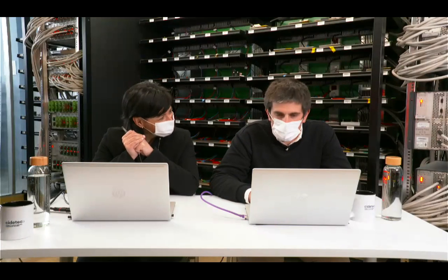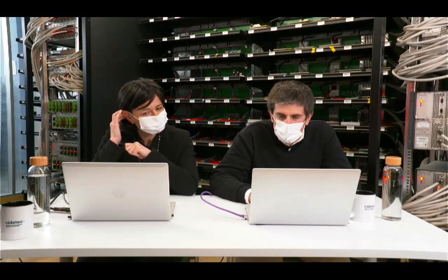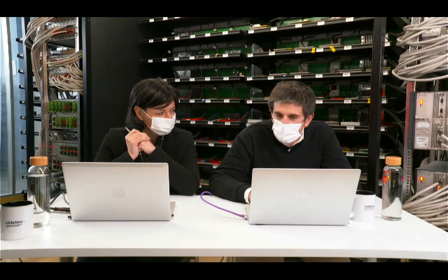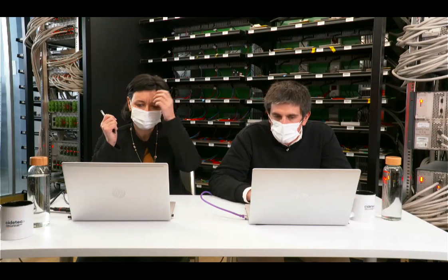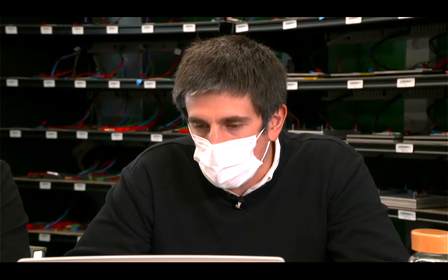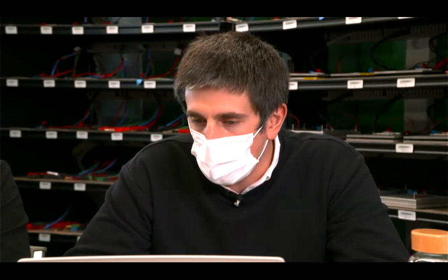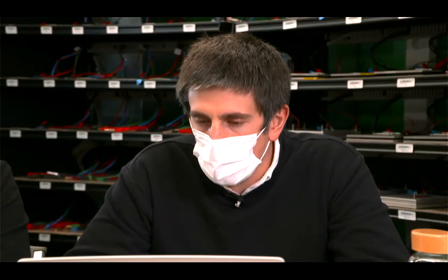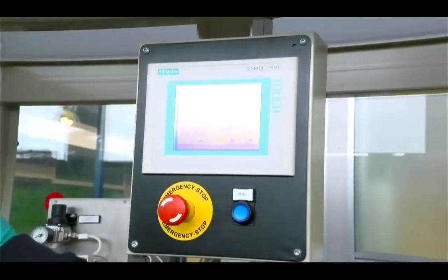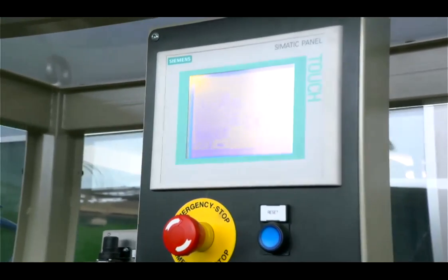Yeah. So okay, there are some questions here. First of all, the first question was how we transfer this stack from the vacuum oven to the electrolyte system. Maybe it was not appreciated, but Iker at the beginning was in the dry room. So the stack, once it is dried in the vacuum oven, is in the dry room conditions. Of course there is some water in the air, but it's very low. In this dry room, we are working with a dew point of -40 degrees, and we are transferring directly from the oven to the electrolyte filling machine. They are doing the filling of electrolyte and making the vacuum and sealing it.